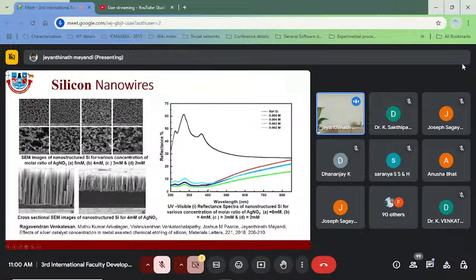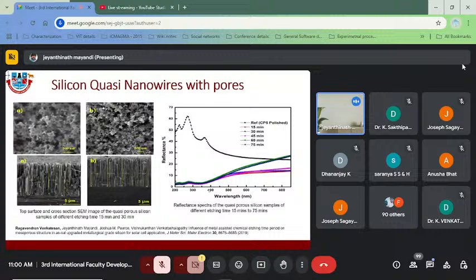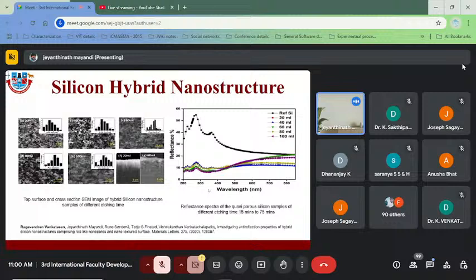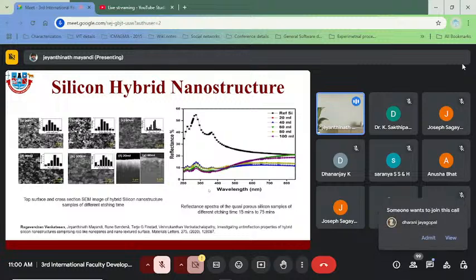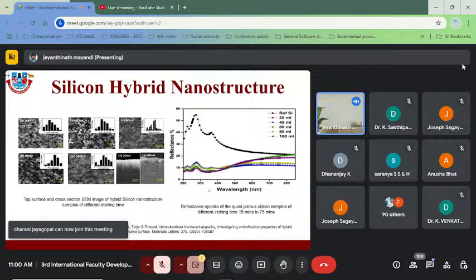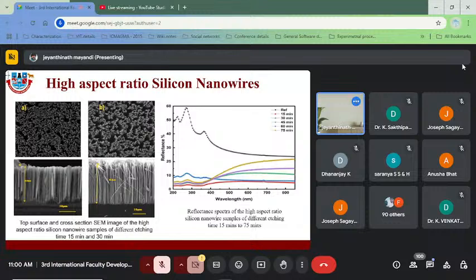And here also you could see that in this region, where the main focus of capturing light is, reflectance has been reduced drastically. These nanostructures really help, and you could change the absorption properties. This is another silicon quasi nanowire porous structure, also published in the Journal of Materials Science: Materials in Electronics, so you could have a reference for this. And also the silicon hybrid nanostructures, where the combination of quasi porous silicon and nanopillars gives another important anti-reflecting property, with rod-like nanoporous and nanotextured surfaces.